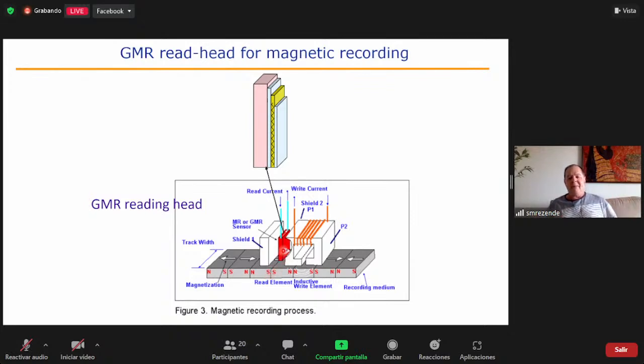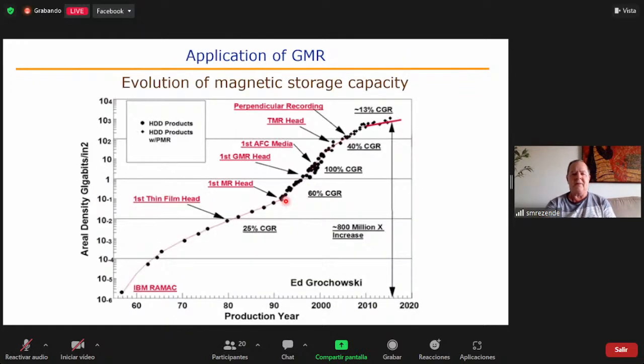Now, in the case of this so-called spin valve sensor, the spin valve sensor is sensitive to the magnetic field, not to the flux. So a small magnetic field, a few oersted, can very easily change the magnetization of the sensing layer, and then it changes the resistance. So if we have a reading current here, the voltage will depend on the resistance, and this is a simple detector for the direction of the magnetization.